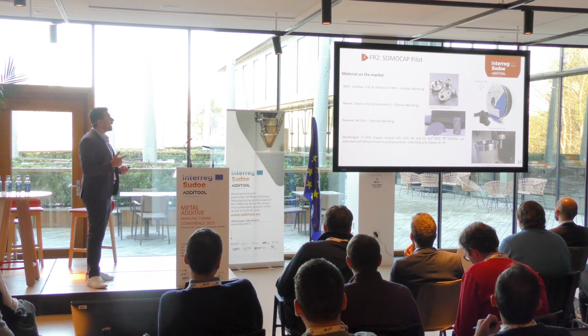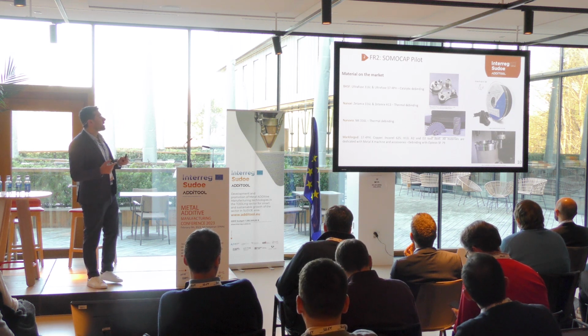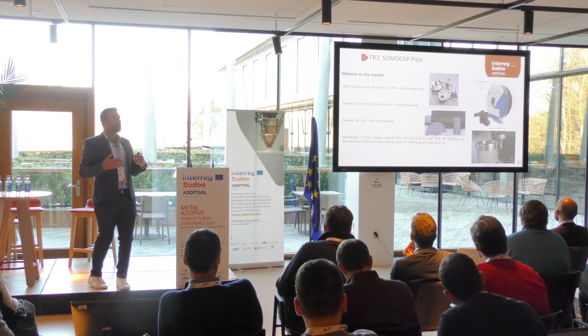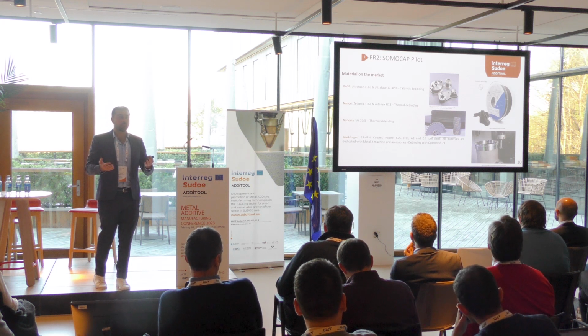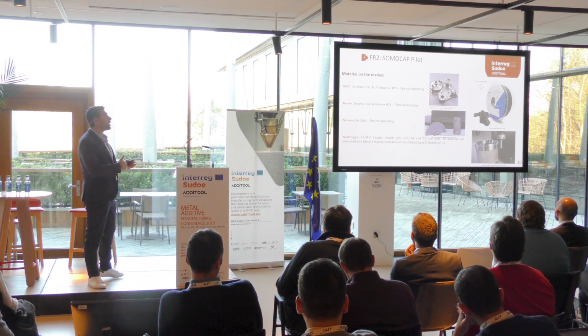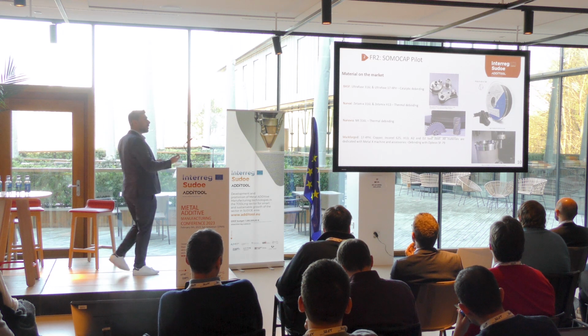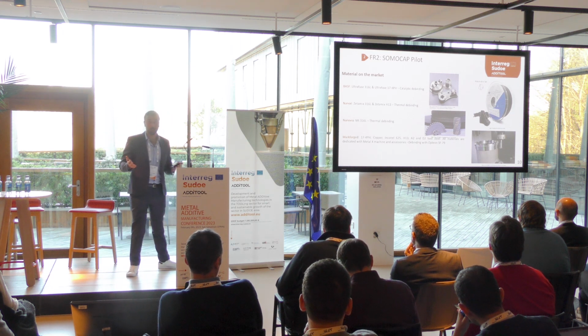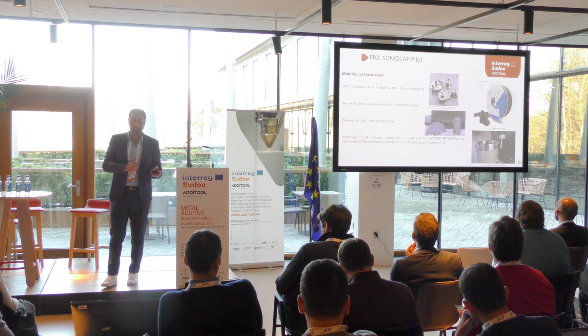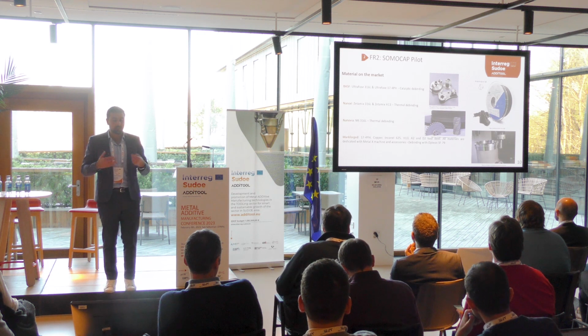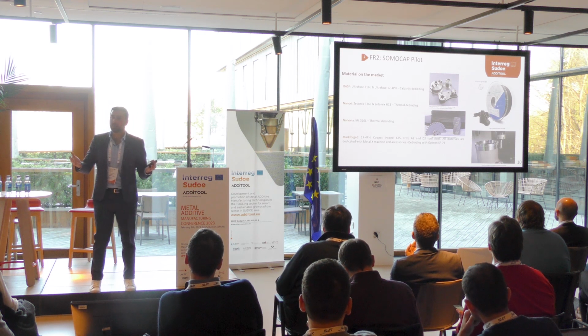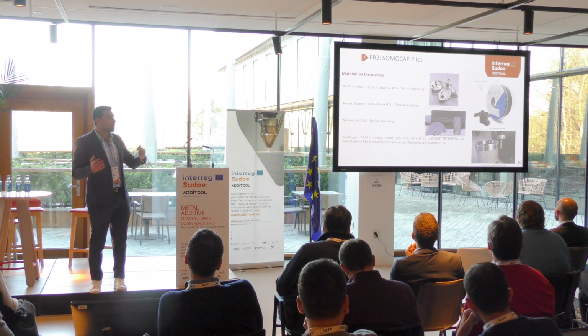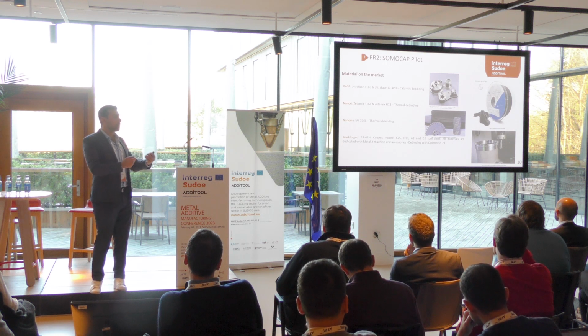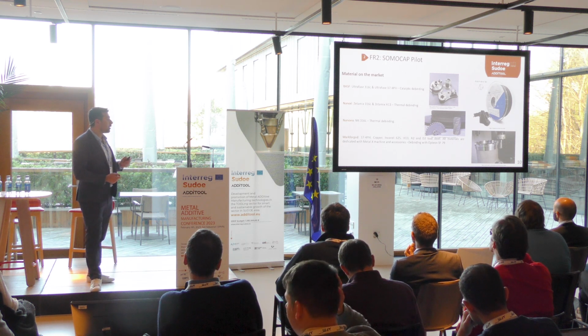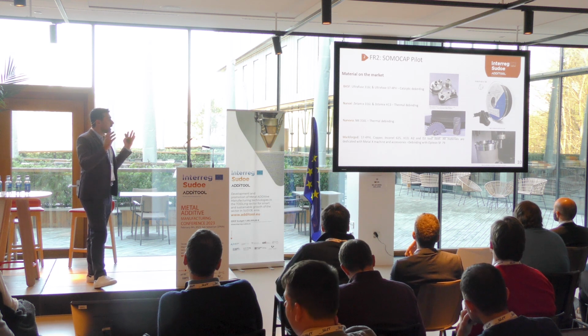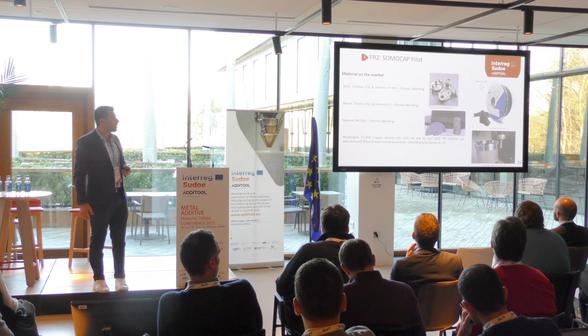You have NanoE and Nanovia that are performing wires and filaments with thermal debinding, so only one oven to do both debinding and sintering. And then you have Markforged with all the value chain. When you buy the machine, you have the washer with Opteon gas, and then you have the sintering oven.